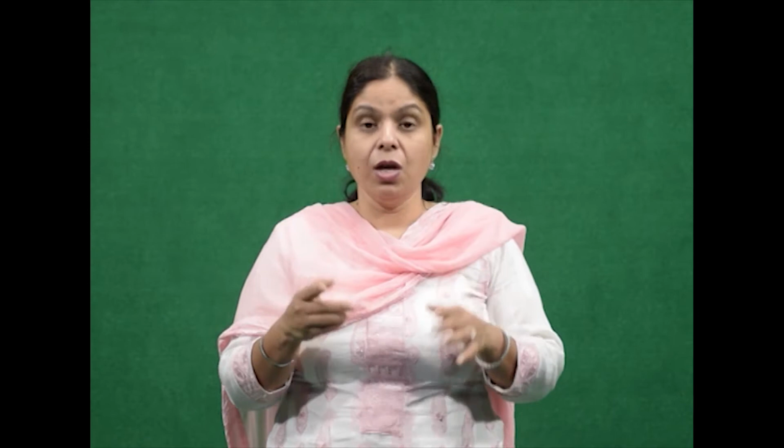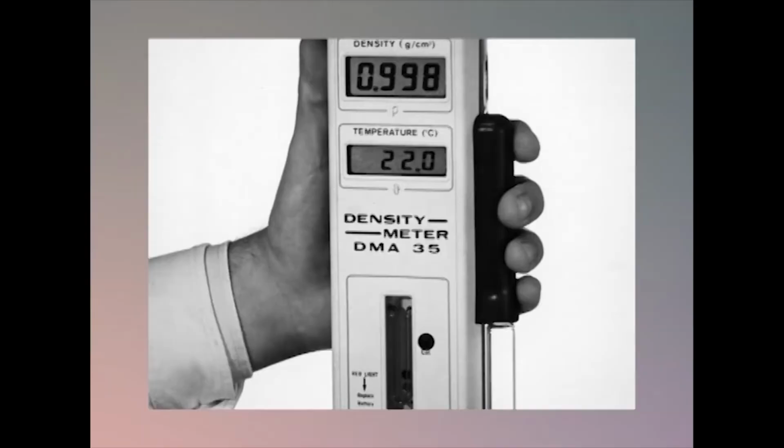Since window glass does not have a uniform density, care must be taken to determine the variation in the density of the known sample from different locations. Also, the surface of the tempered glass is less dense than its interior, so one has to be careful in taking measurements of several known samples.